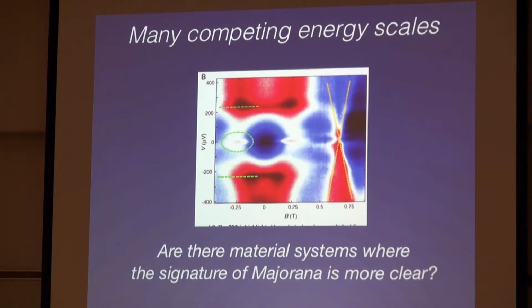But something else happens when you start to see that peak. You can see that these peaks out here, which are the peaks in conductance associated with the superconductivity, start to collapse at about the same time the Majorana peak comes up. What this might be is that, in addition to an energy scale associated with the superconductivity, the induced superconductivity that gives rise to Majorana fermions, there are a lot of other energy scales and things going on in this device that might give rise to a peak at zero field. One of them is the Kondo effect. So one critique of this particular graph would be that as the superconductivity starts to die off as you apply this magnetic field, the Kondo peak, the energy scale associated with Kondo, now becomes the dominant energy scale.